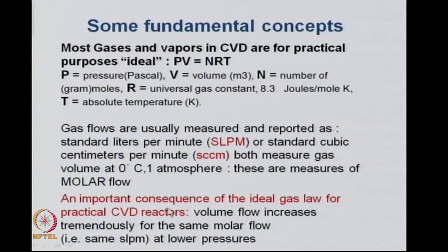An important consequence of the ideal gas law for CVD reactors is that volume flow increases tremendously for the same molar flow at low pressures. So, volume flow will increase significantly at low pressures at the same SLPM. If you have the same flow, standard liters per minute, but you change the pressure from high pressure to low pressure, the amount of volume flow will increase tremendously.